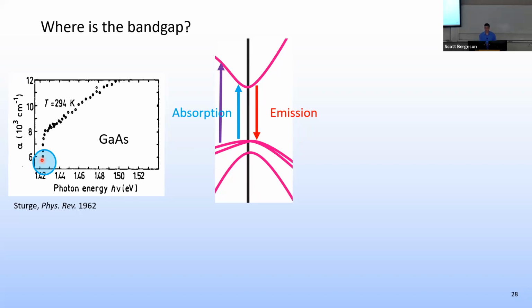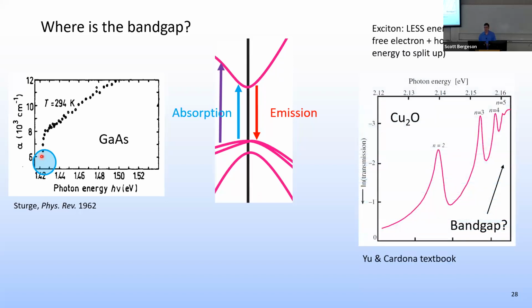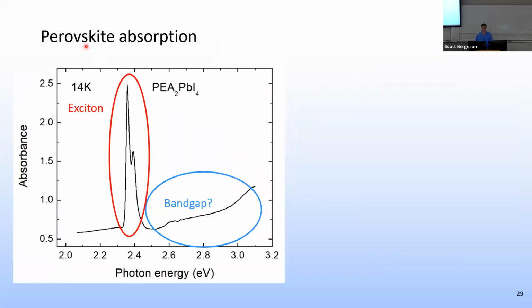You can also, in many materials, look at the emission and look at where the emission happens, and that will also mark the band gap in many materials. But in materials where excitons have big effects, which is the case for these perovskites, as I mentioned, it takes less energy to create an exciton than it does to create separate electrons and holes. And so you get excitonic related peaks here that mask where the band gap is. And you can't even really tell in this material just by looking at the absorption where the band gap is. And that's the case with our perovskite materials as well. So we measure the absorption. These are excitonic related peaks. And then somewhere in here is the band gap, but where?